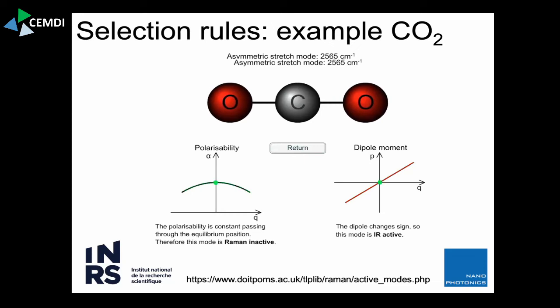So that means you have a symmetric situation here. And regardless how you draw this diagram, if it's symmetric, it has to have a horizontal tangent here. And that's exactly the slope. So that means in this case, the change of polarizability is zero here. And that means this doesn't give you any Raman effect.